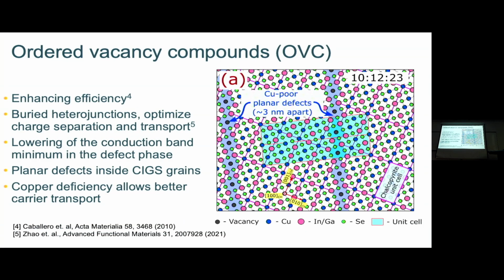And I want to show you why. When you grow it with a deficiency of copper, the material segregates. So you have the normal CIGS stoichiometry here in the white, and you have the deficient copper region segregating into these planes. So they're like buried heterostructures in the material. And these carry, I believe, the charge carriers better out to the electrodes that you need. And that's why it improves the efficiency. So the copper deficiency allows a better carrier transport that allows this material to achieve its very high efficiency. And these are just about 3 nanometers, so it's really small planar defects that are appearing. But the important thing is there are 2 different materials underlying this when we try to understand the dynamics.